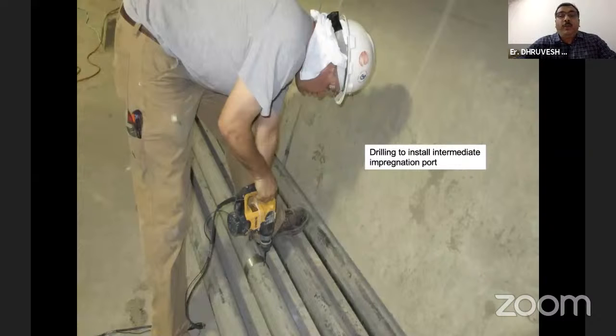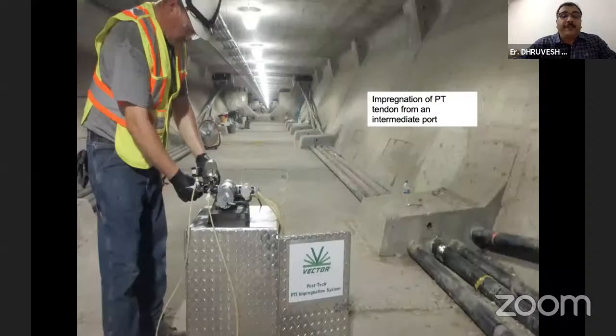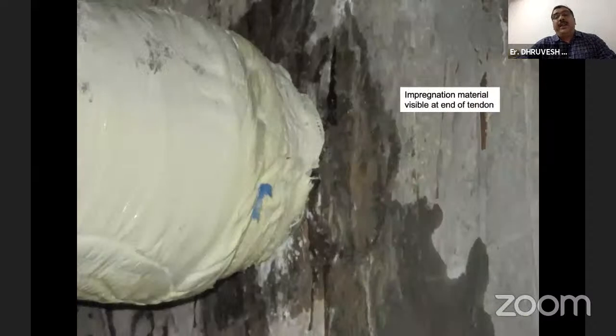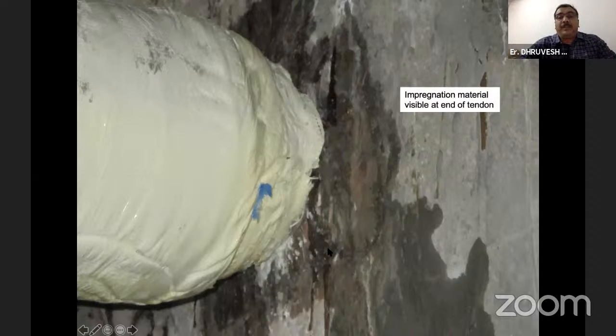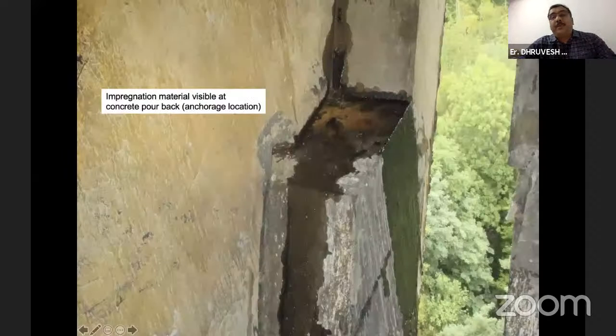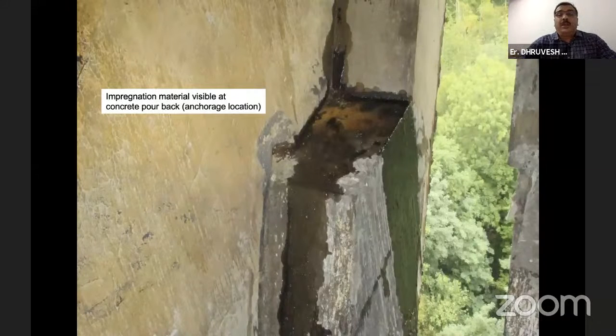So we also do it from the center at other places. We drill the hole and fix the port, and this is the sort of equipment we use, which has a source of grout beneath, and then we pump the impregnation material and check at the other end. You can see at the end cap portion all the cracks or whatever position where the grout is traveling. It is confirming that it has traveled all along the PT strands. This is the other end, where there is a pour block, end block, that also got some from the anchorage end and the complete pour block. There was a gap, so the material is oozing out.